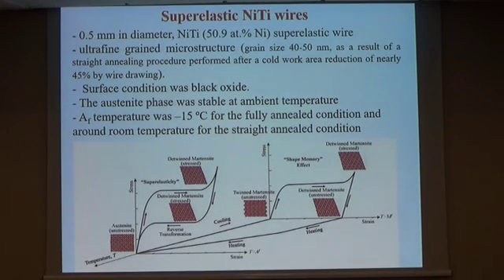This shows some data of the superelastic nickel titanium wire we use, 0.5 mm in diameter, with an ultrafine grain microstructure. The surface condition was black oxide, and the austenite phase was stable at all the temperatures used for the test. So we are in this situation.